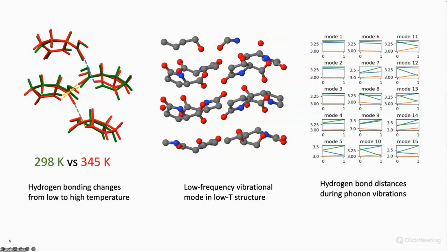So over here you can see, for all the structures, we have measured the distance of these hydrogen bonds. And you can see for mode number 12 up here, for example, the blue hydrogen bond here becomes much shorter when we actually perform this normal mode vibration. So that could be part of the triggering normal modes that transform one form into the other. But we haven't found one mode that can explain the entire phase transformation. So it seems that there has to be a combination of these modes in order to bring the low temperature phase to the high temperature phase.